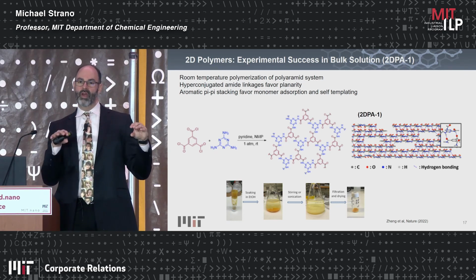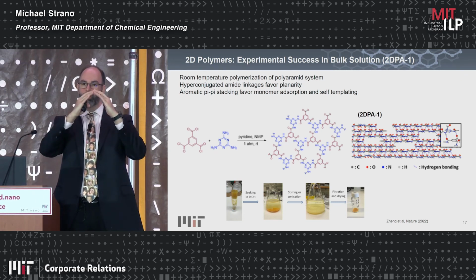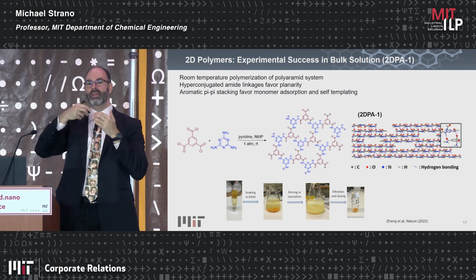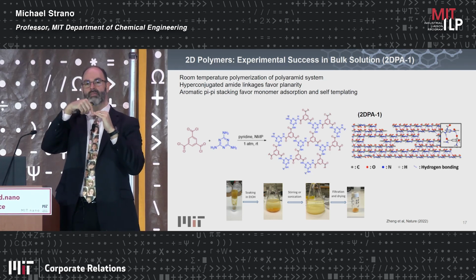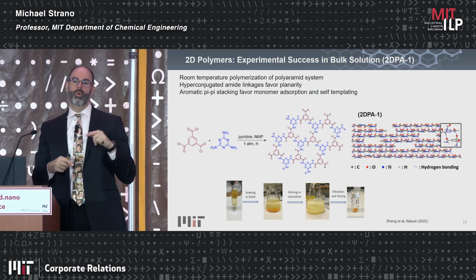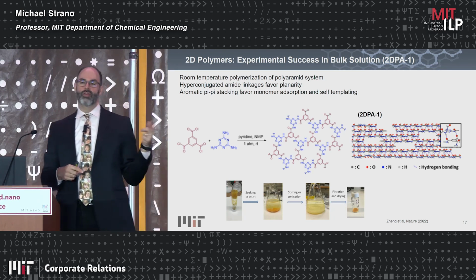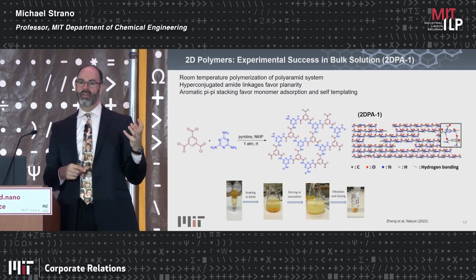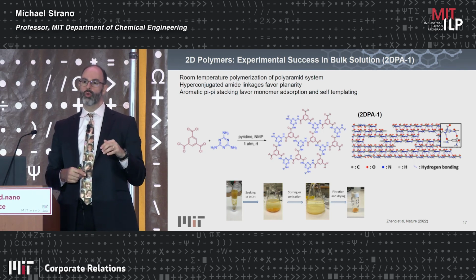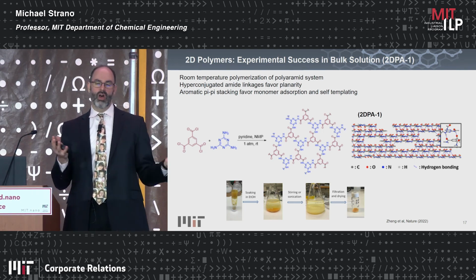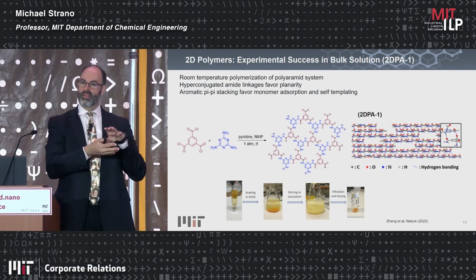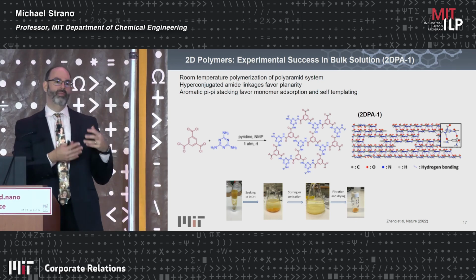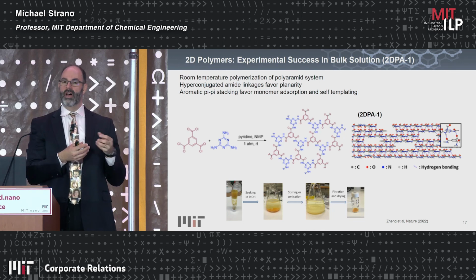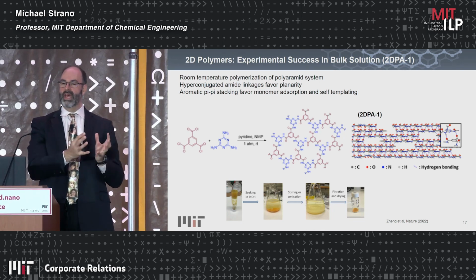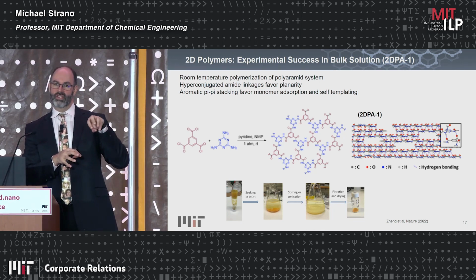Then when we made membranes, we did this bulge test where you make this bubble. That's mainly a mechanical test. We were pressing on it to get mechanical properties. When we went back almost a year later, we found those bubbles did not collapse. They actually kept their air, very unusual for a polymer. Polymers around you, even your sandwich that you put into a plastic bag, air still does get through that. If you think of like a plate of spaghetti, it has these little volume crevices where gas can go inside.